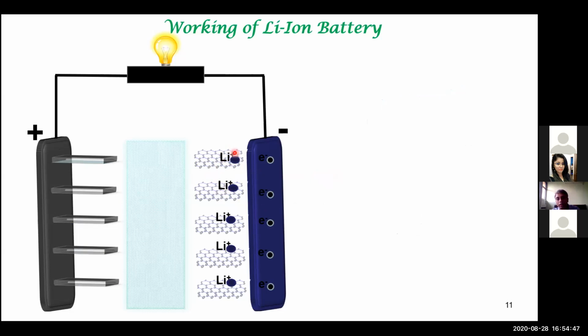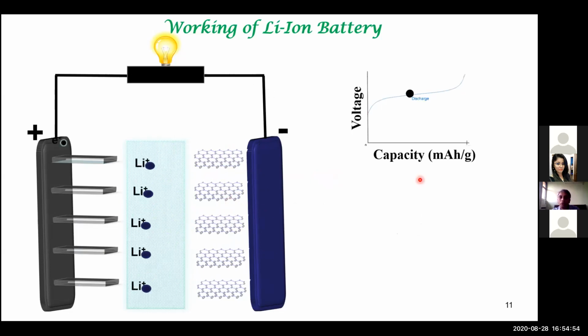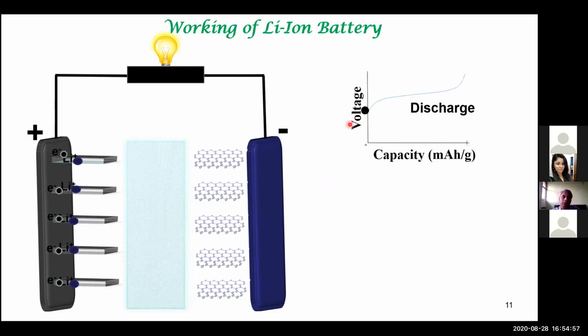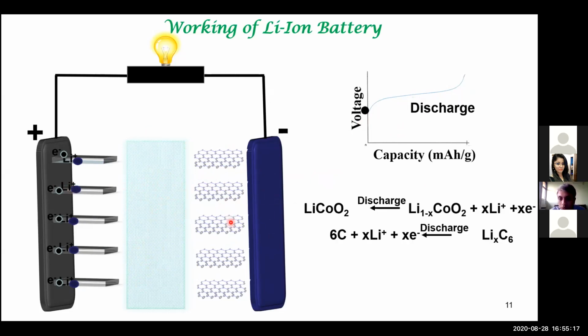During discharge, I have lithium ions in the graphite material, which is intercalated, and the voltage comes down as the battery discharges. The lithium ion goes through the electrolyte. The electrolyte is an ion conductor, whereas the electrode is an electronic conductor. The lithium ion goes across the electrolyte and gets intercalated again into the transition metal oxide. This is an exothermic process, which is why I am able to get energy out of the system. During charging, I have an endothermic process; during discharging, an exothermic process, which gives rise to a voltage.